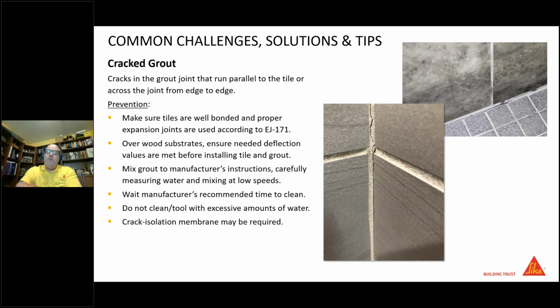So those are the typical two types of grouts. I can tell you when you've got a grout that cracks from edge to edge, so it's between the tiles, going from one tile to the other, that's typically a shrinkage grout. And that typically means that your grout was mixed too wet, you got on it too soon, added too much water in your cleanup, or you used the wrong grout. So you maybe used an unsanded grout in a 3/16 inch grout joint, and that grout is not made to withstand that width of a grout joint, so it shrank. Hence, the sanded grout would have been the proper choice for that.